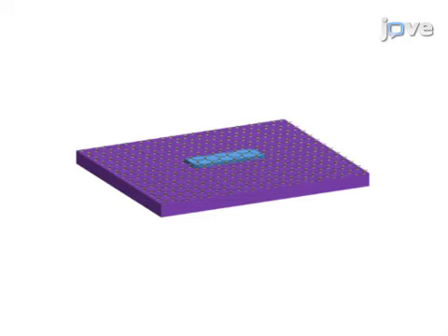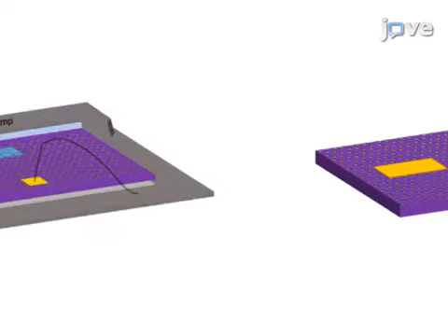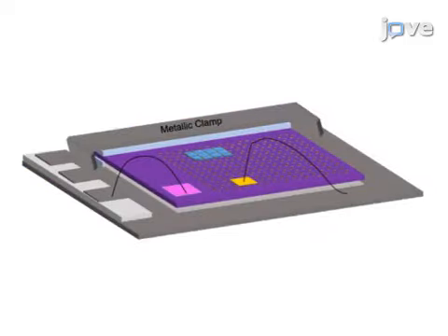The second step is to clean the graphene hexagonal boron nitride silicon dioxide heterostructure in an argon-hydrogen environment and evaporate a gold titanium contact pad onto graphene. Next, the heterostructure is assembled into a gate-tunable device by wire bonding it onto appropriate terminals on a scanning tunneling